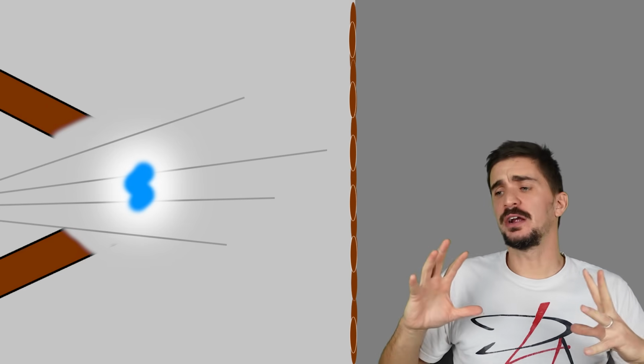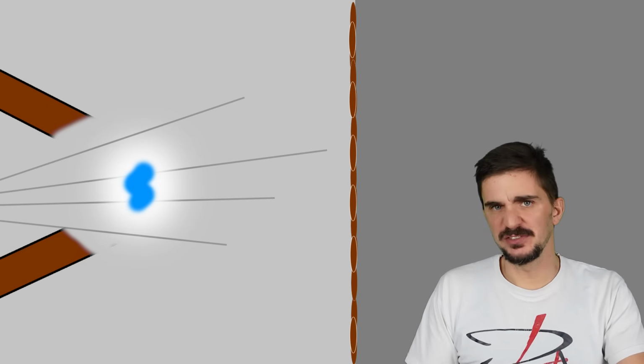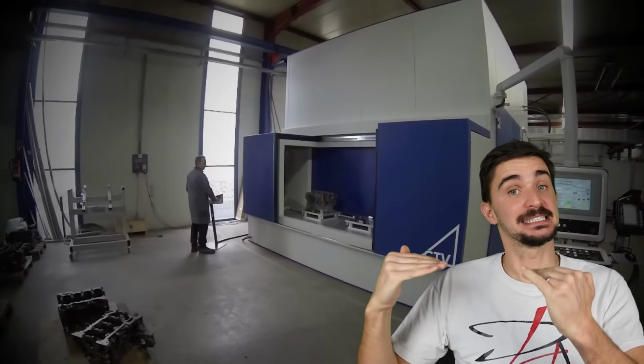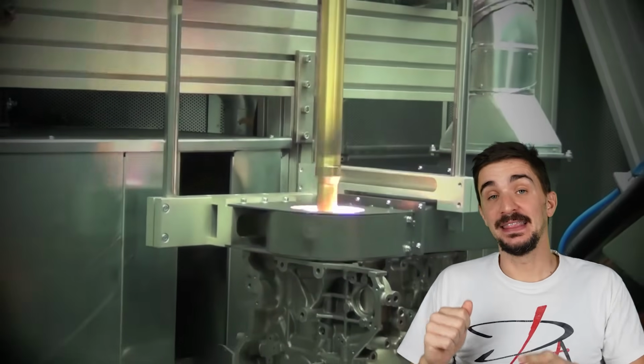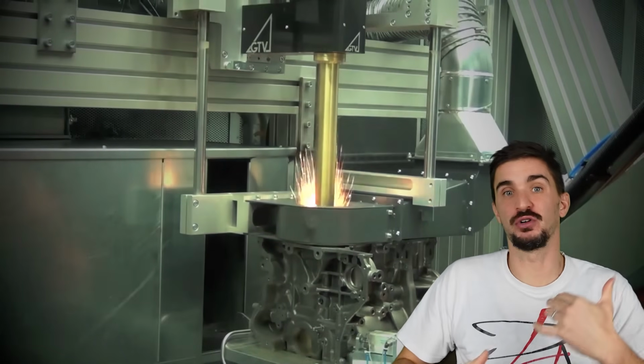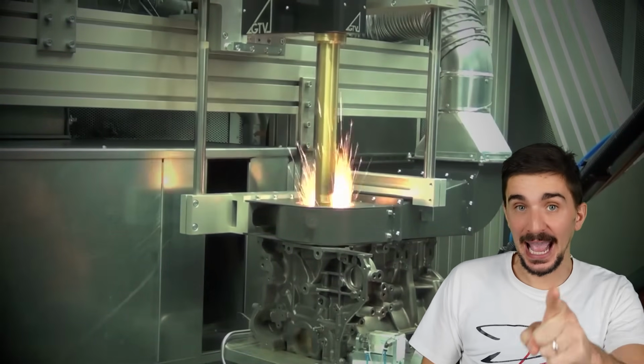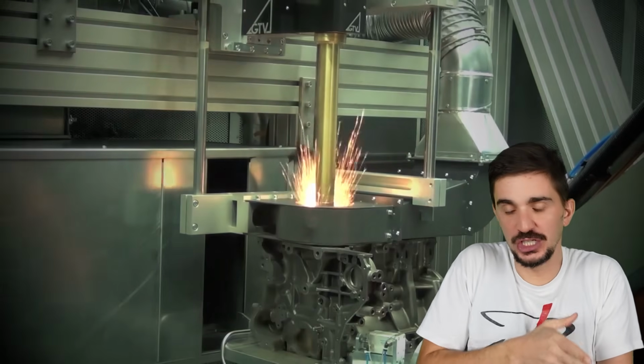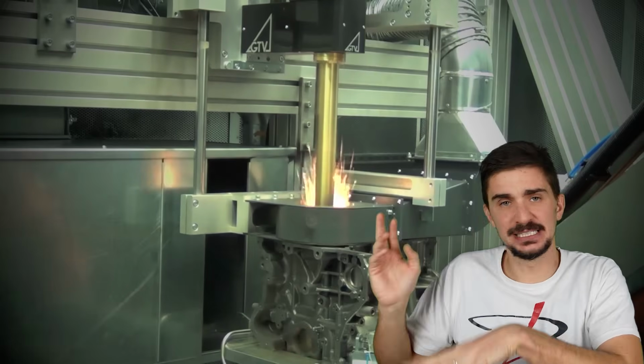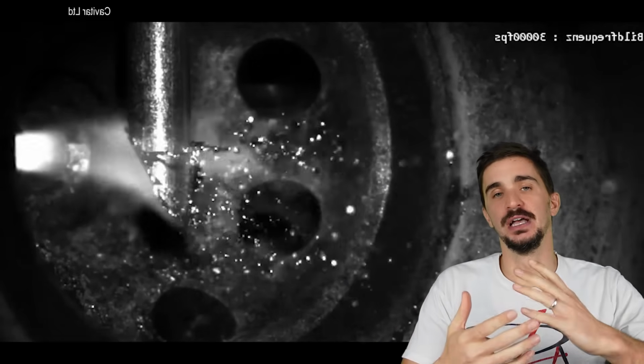Now, thermal spray coating requires a massive initial investment in very expensive machinery, but in the long run and at sufficiently high volumes, it's actually more cost-effective per cylinder than an iron liner. The added benefit for manufacturers is that the process is generally very fast, easily scalable, and it's easy to adapt from one engine configuration to another because the very same machine can do all kinds of different engine blocks with minimal downtime in between. The end result is again, of course, a very thin coating, which is supposed to improve heat transfer, reduce friction, and improve durability.